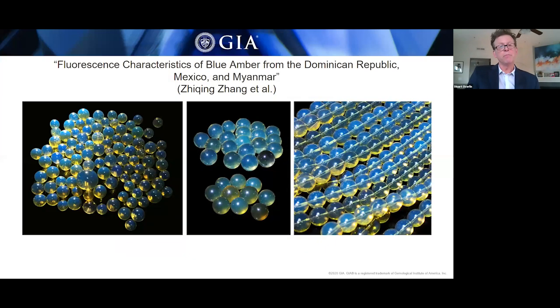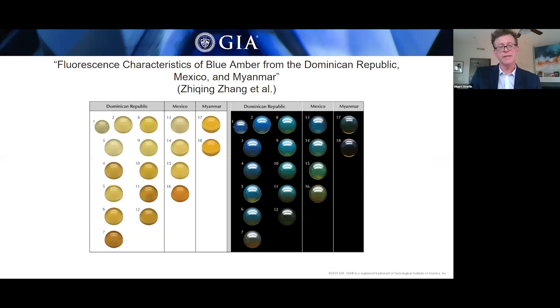The next article is on blue amber, which shows this very strong blue fluorescence under UV light. Ziqing Zhang, Andy Shen, and co-authors at the China University of Geosciences in Wuhan provide a means of separating blue amber from the 3 main localities. Those are the Dominican Republic, Myanmar, and Mexico. And they were able to separate the geographic origin of these blue ambers using a combination of observation, UV-Vis and IR testing, and excitation emission mapping.